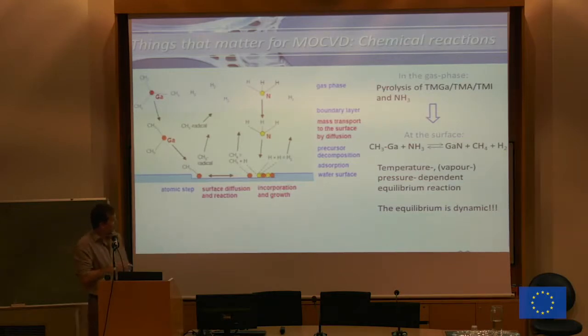So that at the surface, after pyrolysis and diffusion, you have this reaction here. So it is monomethyl gallium and ammonia, and it goes to gallium nitride and methane and hydrogen. These are produced at the site of reaction. Now, very important to understand is that this reaction is an equilibrium reaction.